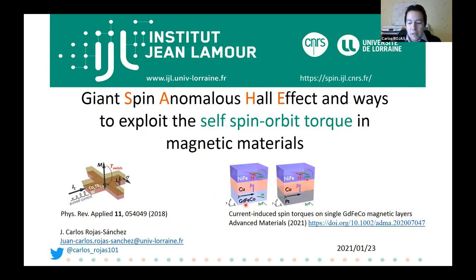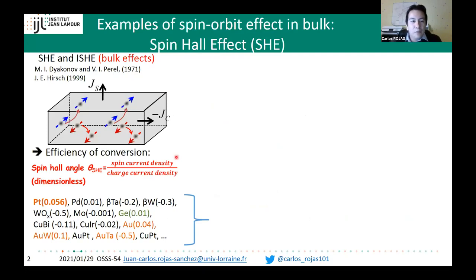Let's remember the symmetry of the spin Hall effect. When we have a material such as a heavy metal with strong spin-orbit coupling and inject a charge current, we get a transverse spin current. The polarization of this spin current is perpendicular to both the charge current and the direction of the spin current. The efficiency of this charge-to-spin current conversion is called the spin Hall angle, a dimensionless parameter. In our community, we have studied many materials and tried to engineer interfaces to improve this efficiency.